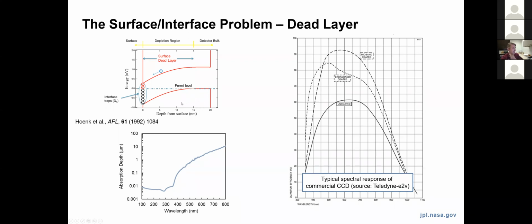But that periodicity and perfection essentially ends once you get to the backside of the detector. So you run out of silicon atoms. This is the dangling bond problem. It's not literally a dangling bond in the sense that the silicon is typically bonded to something like oxygen or hydrogen or carbon, but the breaking of the periodicity in the lattice leads to the presence of interface states which can trap charge. And so what ends up happening is the accumulation of this trapped charge bends the conduction band and valence band energies as a function of depth from the surface, and you create a potential well that ultimately will trap charge carriers that are generated in the vicinity of the surface.